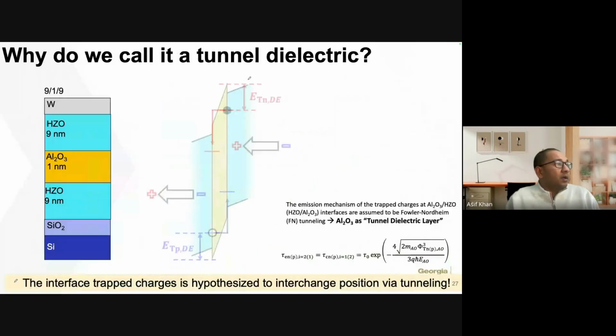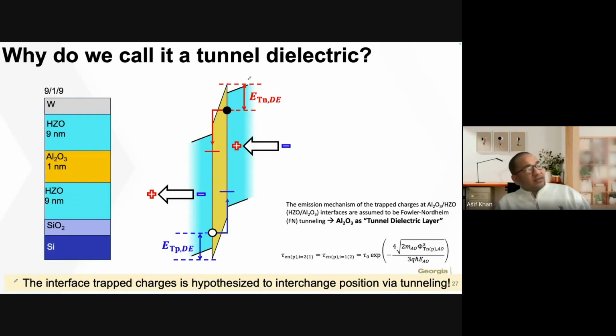All right. So that was an interesting observation, and we published it in IEDM in 2023. And there were a lot of questions about what the mechanism is for the increase of the memory window. I'll not go into the details, but the main idea is that we think what is happening is that at this interface, we are essentially accumulating a lot of mobile charge that gets trapped here because of the polarization of the ferroelectric material.